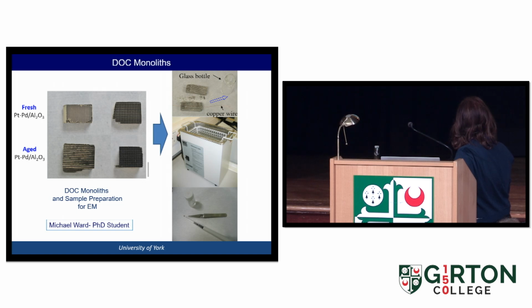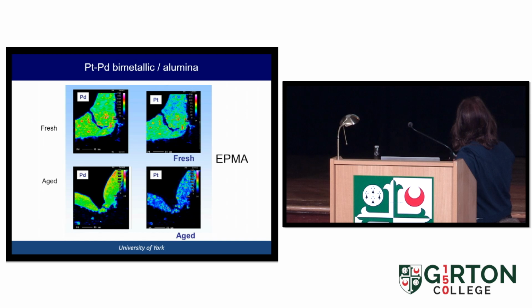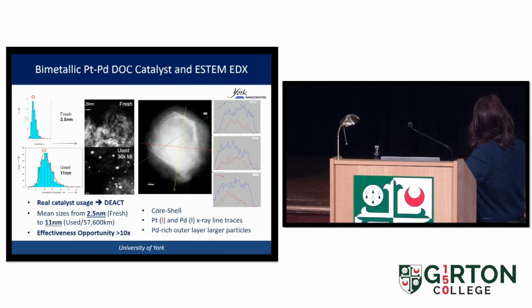My student actually did some work on this. Immediately you can see both palladium and platinum have sintered a lot, but it doesn't give you all the atomic details, so we need to go to the atomic details. It shows that in the fresh catalyst, the particle size is about 2.5 nanometers, and after 36,000 miles, they've grown to 11 nanometers. In other words, they have sintered and they have lost surface area.